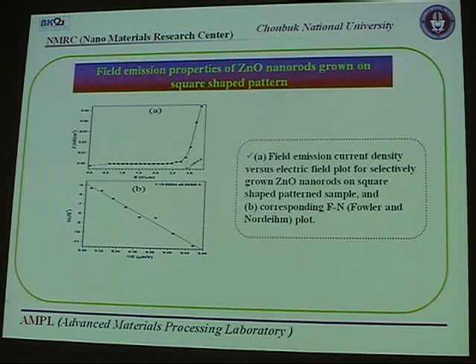Further device application is done by making a field emission device. We used the zinc oxide coated silicon substrate, and the top electrode is phosphor-coated ITO glass substrate to construct the field emission device, which shows a low turn-on field of 2.85, and the FN plot is just a linear plot.